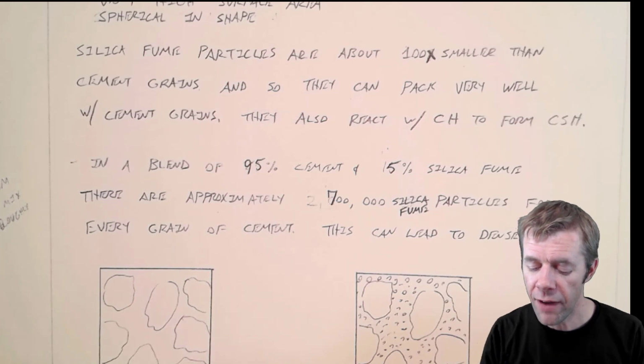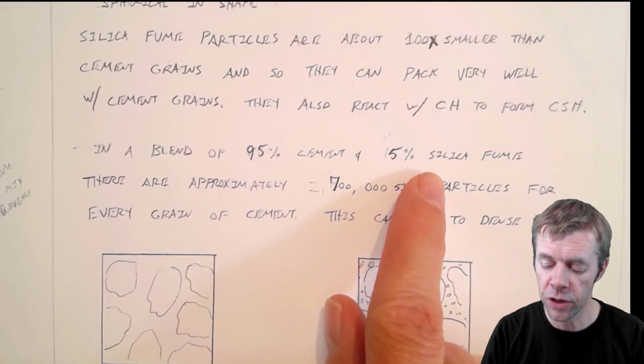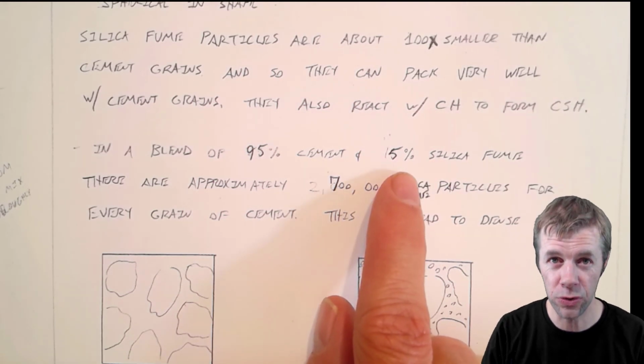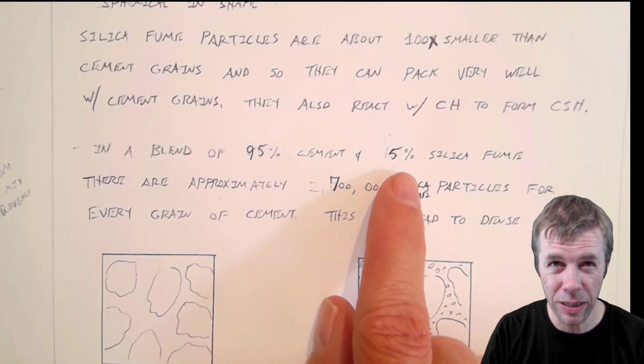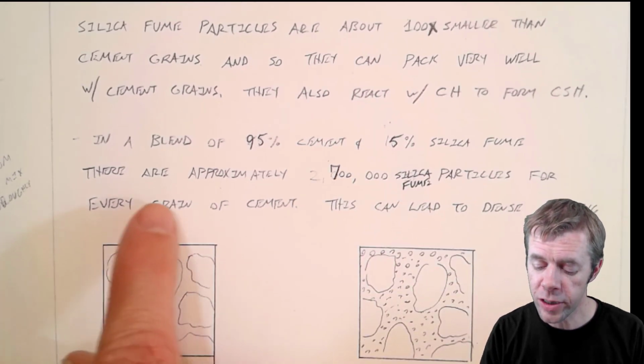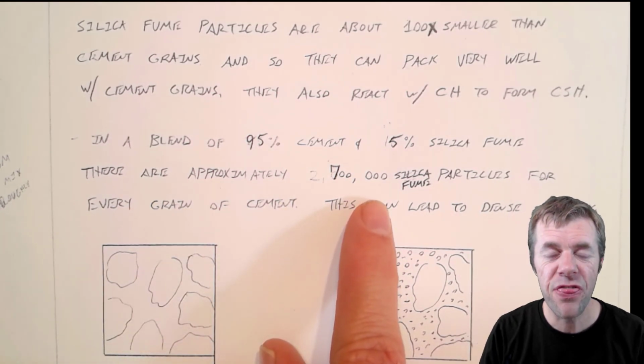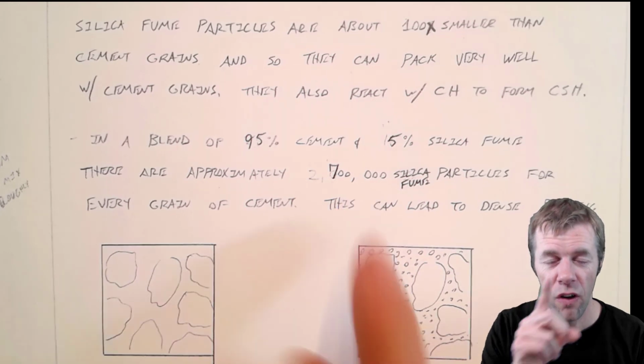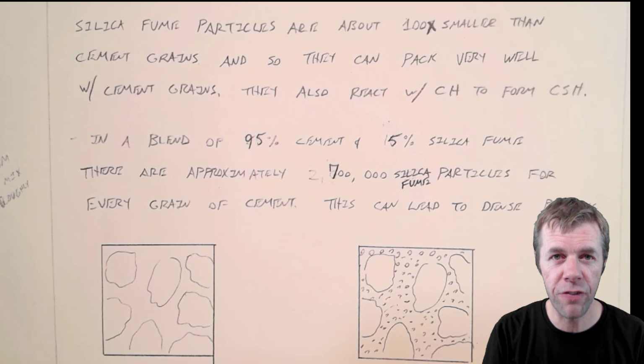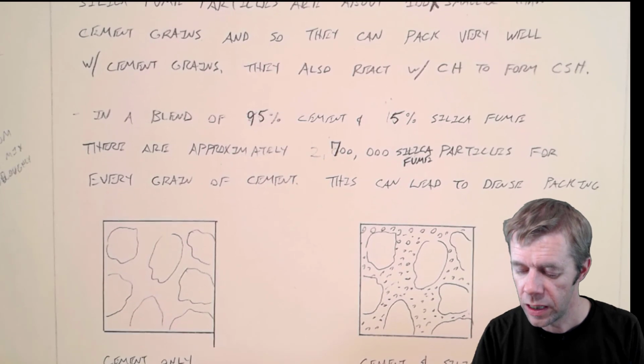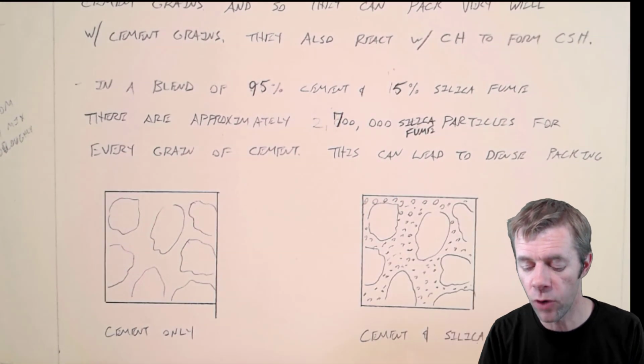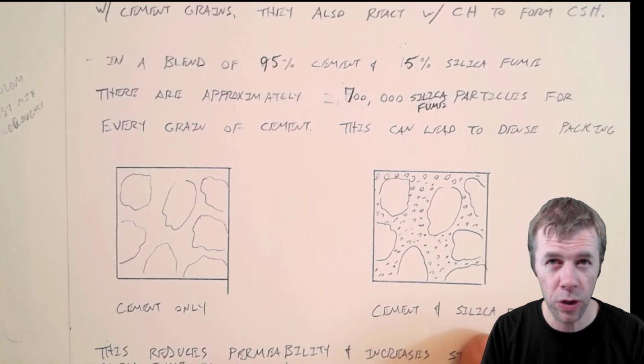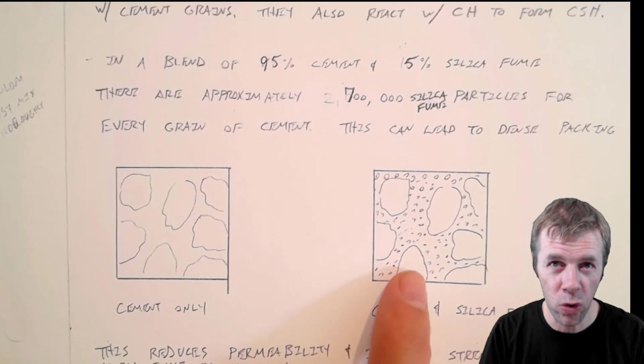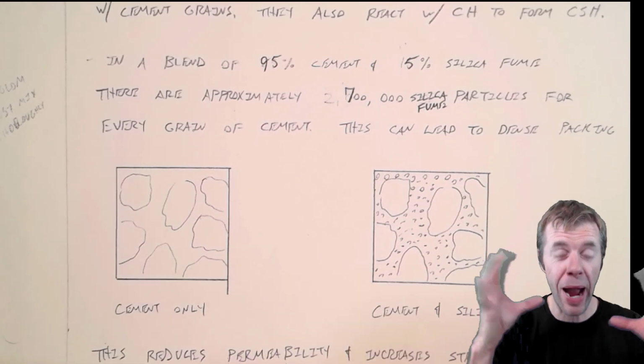Let me show you what I mean. If I have a blend of 95% cement and 5% silica fume, and by the way, this is about the highest dosage that's used of silica fume. 5% makes the concrete extremely sticky. But there's approximately 2,700,000 silica fume particles for every one cement particle. And this can lead to extremely dense packing. What do I mean? If I have only cement, it looks like this. If I have this cement plus silica fume, look, for every one of these particles, I got 2,700,000 smaller ones to pack around it, okay?